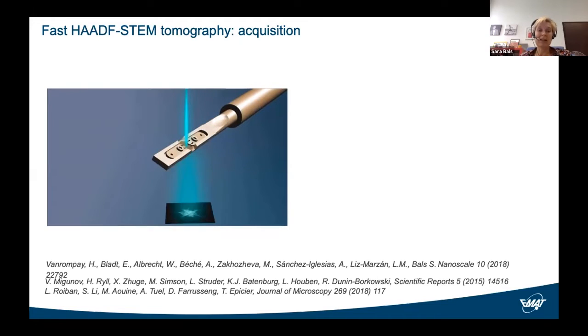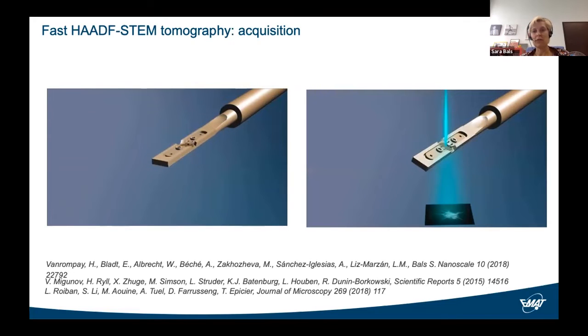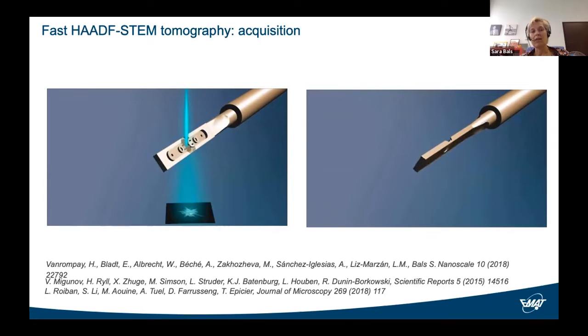And 1 hour is simply too long to capture the fast transformations that these nanomaterials will undergo when they're exposed to more realistic conditions. So in order to overcome this challenge, we need to drastically accelerate the acquisition of images. And so therefore, what we are currently doing is we simply leave our holder tilt continuously in a microscope. And rather than capturing images, we are capturing a movie.